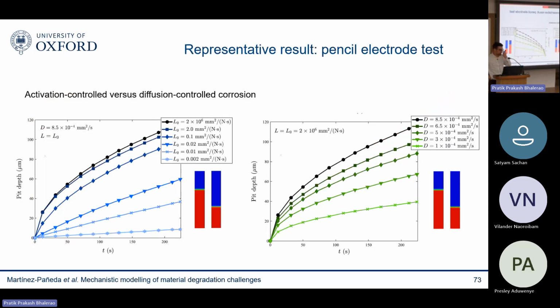And you can also show that the model can naturally capture the transition from activation control corrosion to diffusion control corrosion. You can see here, this is the linear behavior typical of activation control corrosion. And then eventually, if you ramp up your corrosion current density, you get to this regime of diffusion control corrosion. Without having to make any criteria, any decisions, the model will just capture that naturally.